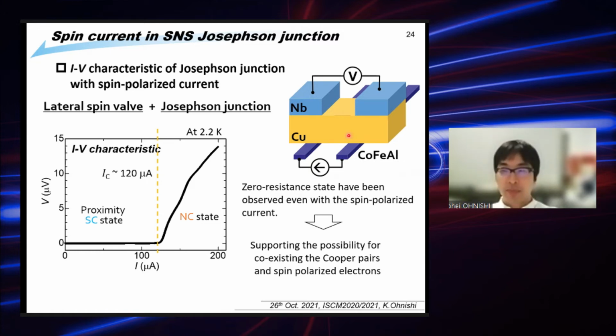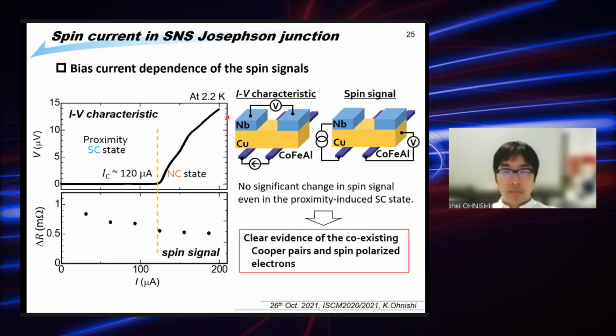And also we have to confirm the spin transport in this copper layer. As I said, to confirm the spin transport, we measure the spin signal, a non-local spin valve measurement, by this probe configuration. By this probe configuration, we can measure the spin signals. And the spin signals have no significant change below and above the critical current. This means that below the critical charge current, the spin information from the left-hand side can transfer to the right-hand side, and also the supercurrent can flow from the left-hand side to the right-hand side. These two data, this figure, are clear evidence of the coexisting Cooper pairs and spin polarized electrons in the copper layer.